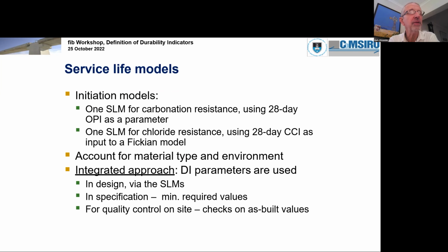These are very simple models. More complex ones are being developed now, but really these simple models have worked extremely well for us over the period of time. They're initiation models at this stage. There's one for carbonation resistance, for which we use the 28-day OPI as a parameter, and one for chloride resistance, for which we use the 28-day chloride conductivity as input to a Fickian model. We have to make some modifications there for chloride binding by effectively aging the value. But that we could talk about at a separate time if needed.